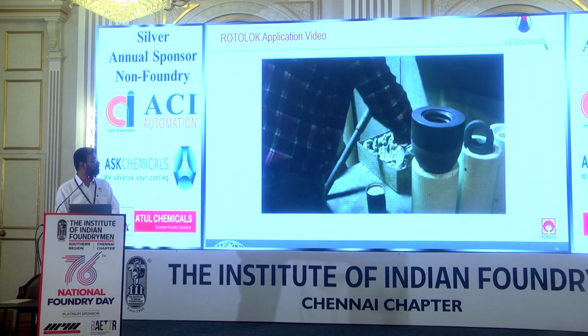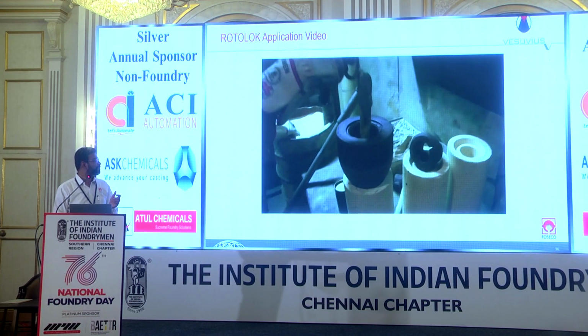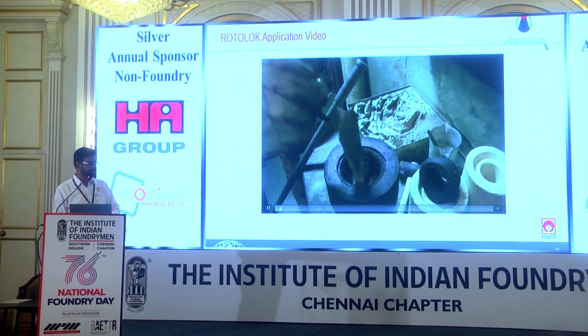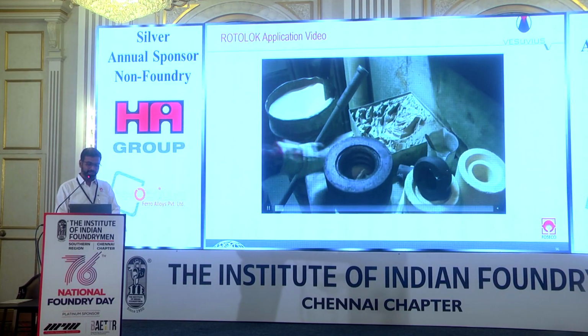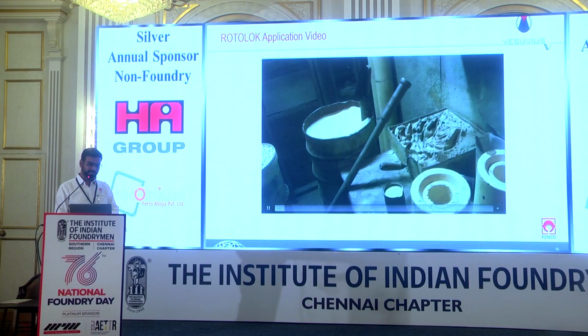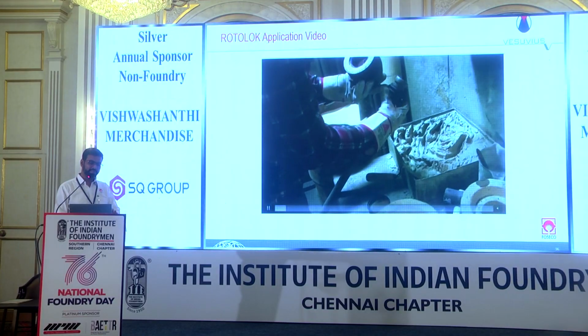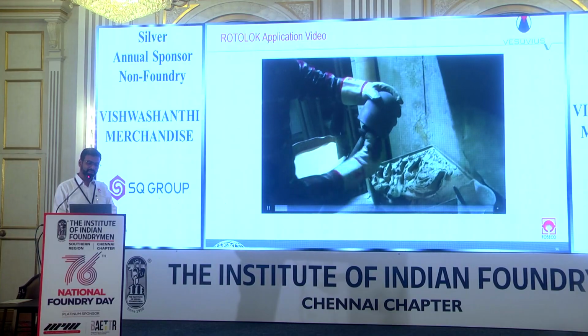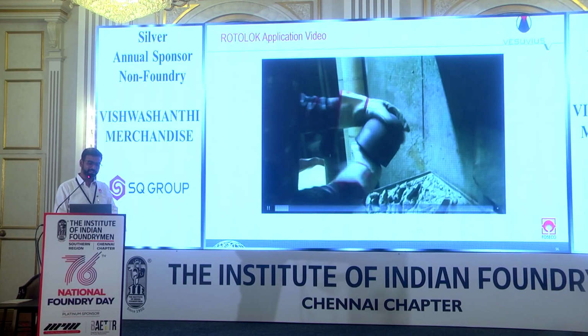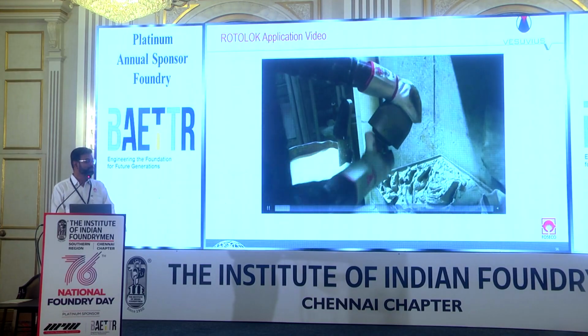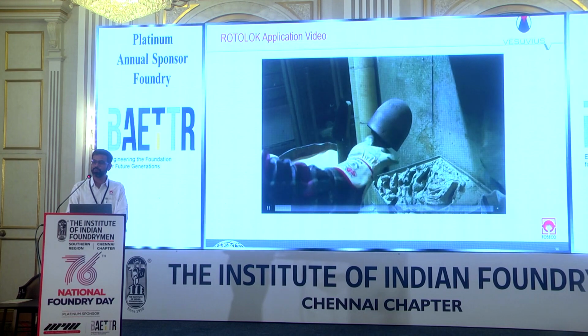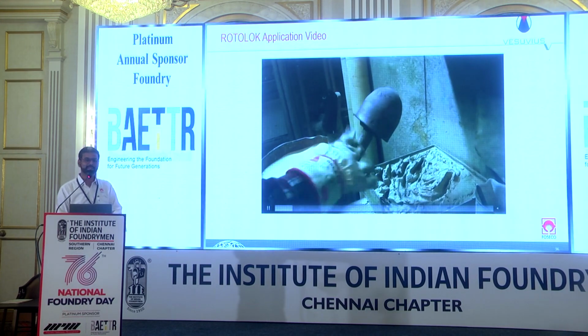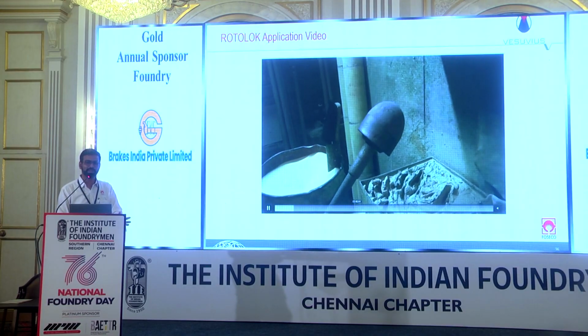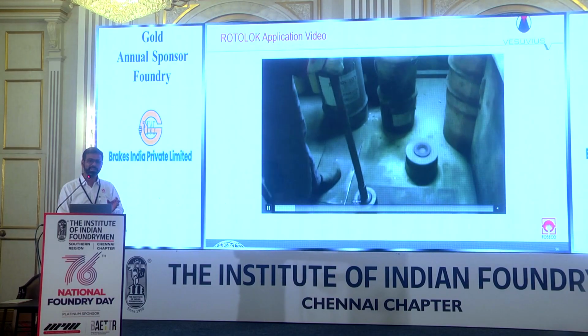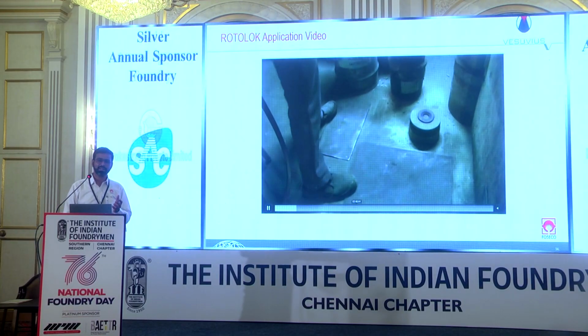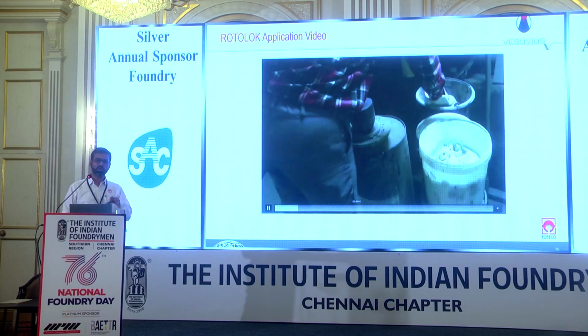See, there is no thread on the metallic rod. However, there is a separate insert which we need to use. So this is the support rod, a metallic rod without threads. For threads, we have to use another product which is an insert. It will go first and then the stopper will be applied on this. What is the use of this? During pouring, steel is poured at more than 1500 degrees Celsius. At that high temperature, the expansion of the metallic rod is more as compared to the stopper, and because of the higher pressure, the stoppers tend to get cracks, and metal will penetrate, or the stopper itself will block the flow of metal.